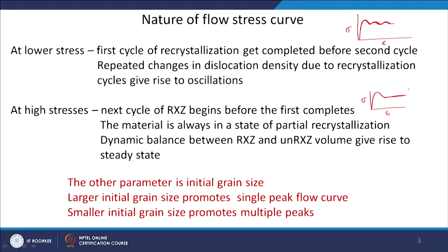In oscillation, after completion of one cycle the whole material gets recrystallized more or less, then the next cycle again the dislocation density increases and recrystallization happens again. At lower stresses — that means lower strain rate and higher temperatures — you have sufficient time to build up the dislocations and complete each cycle. At higher stresses — higher strain rate and lower temperatures — you will have this one single broad peak with continuously ongoing recrystallization in some part of the material.